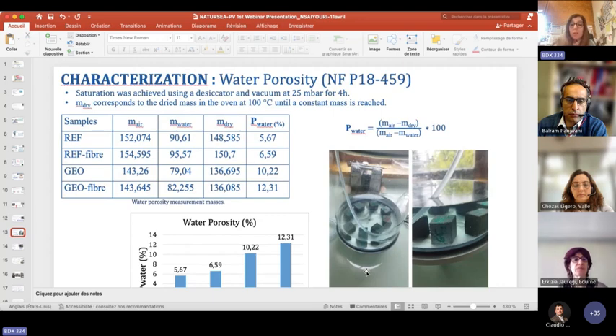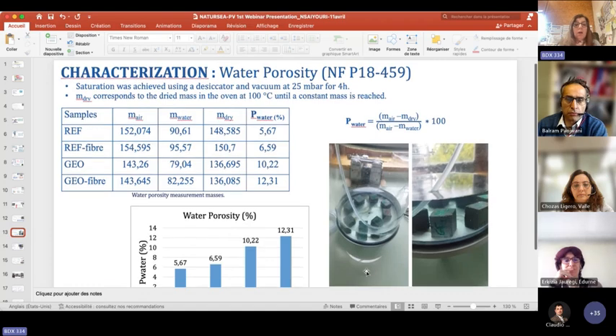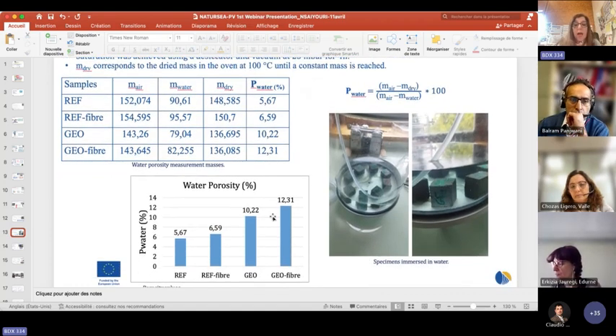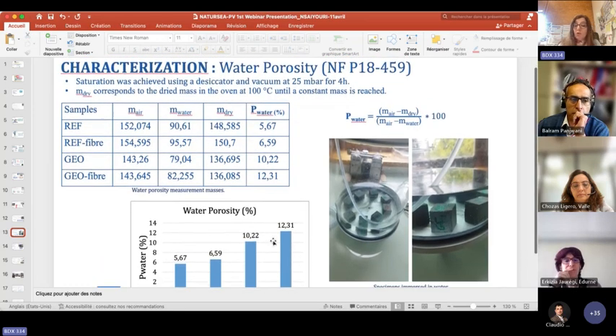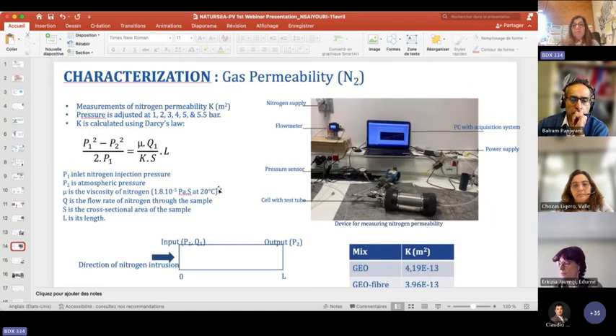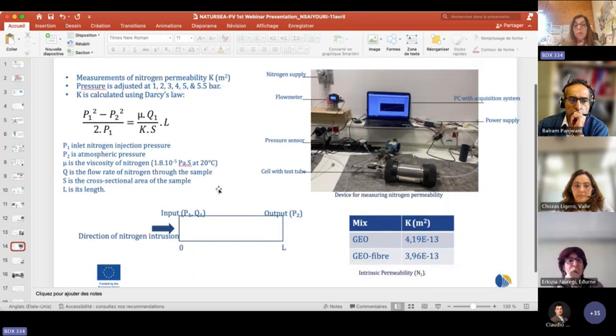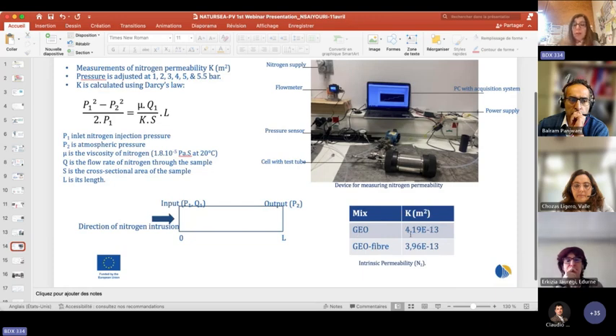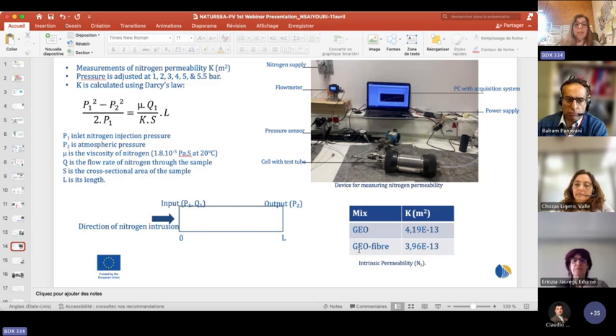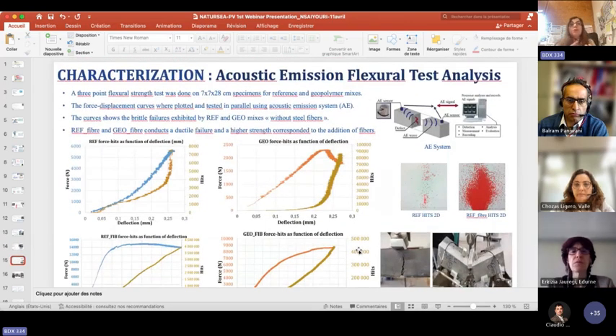Other measurements like water porosity, with the standards, not usual standards, we are about 5 to 12% porosity by water. We also did the gas permeability, which is complementary to transfer properties of the geopolymer, ultra high performance geopolymer, and we could measure some values for geo without fiber and with fiber about minus 13 for intrinsic permeability in square meters, which are usual values, and so we can just show this. We can verify that we have good, expected values.